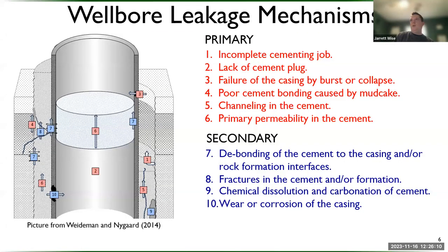All right. So a broad overview of the leakage mechanisms that at least we were considering in our work is shown on the screen. There's primary leakage mechanisms, which include incomplete cementing job, lack of cement plug, failure of the casing by burst or collapse, poor cement bonding, channeling, or just permeability in general. Secondary ones include debonding of the cement, fractures, chemical degradation of the cement, or even wear or corrosion of the casing.